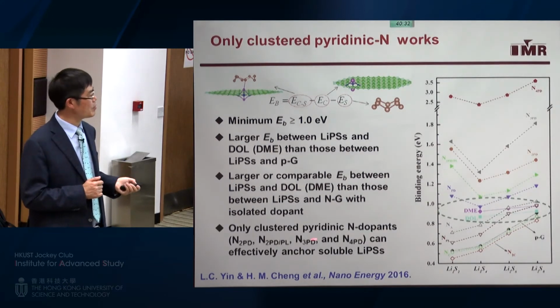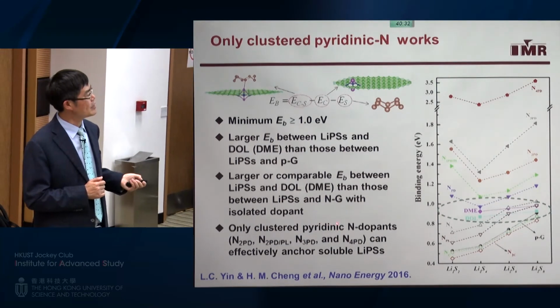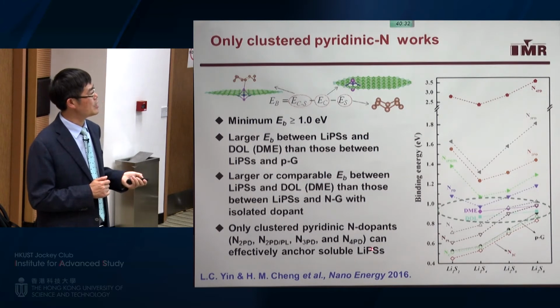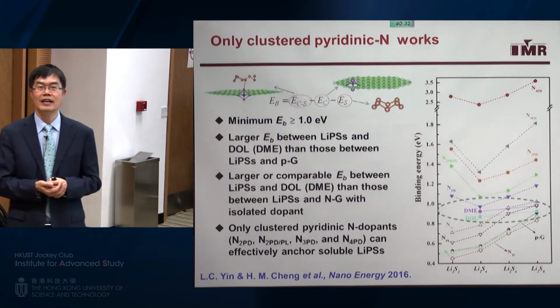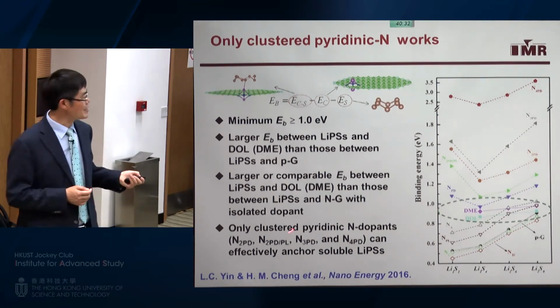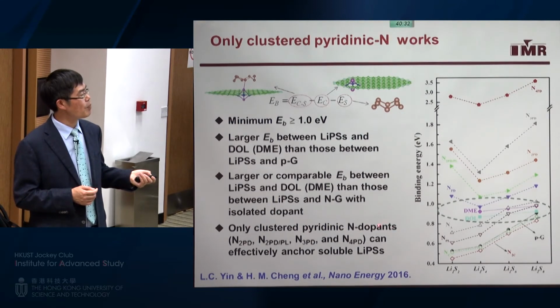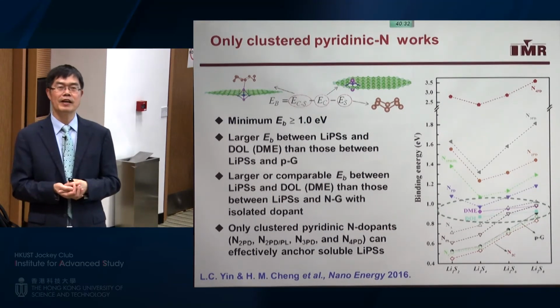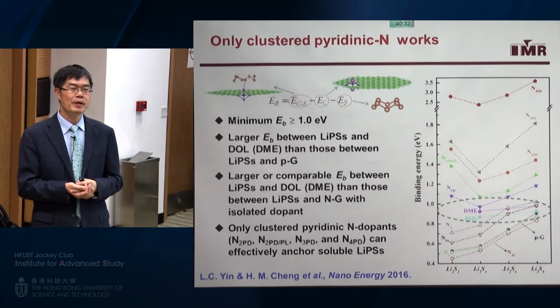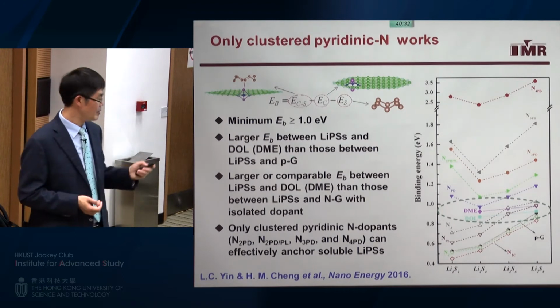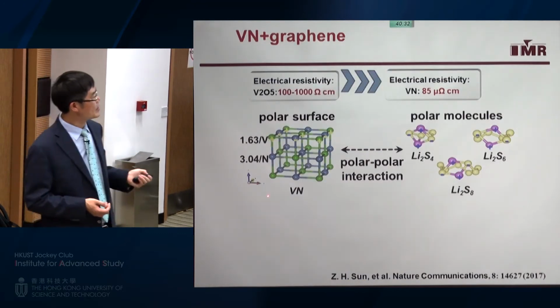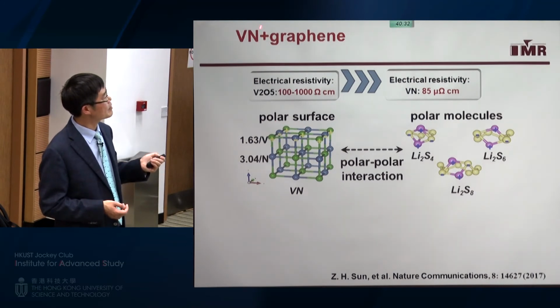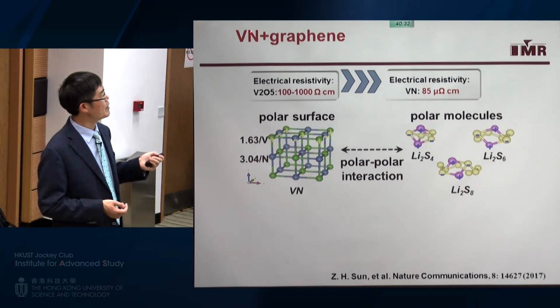However, after calculation, we found that only clustered pyridinic nitrogen doping, this part, has higher binding energy between the lithium polysulfide and the doped material. However, this clustered pyridinic nitrogen doped carbon material is very difficult to obtain. We have tried many experiments, but it's not so successful. So very recently, we are thinking to use this polar surface of nitride, this vanadium nitride with graphene material.